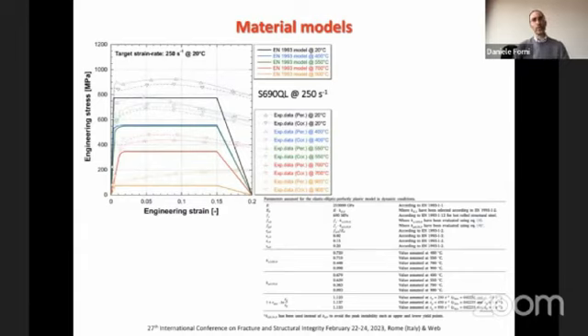So in the first case, for the elastic perfectly plastic approach of Eurocode 3, we have reported an example of the S690QL at 250 strain per second, and we can see that the model we have calibrated can safely predict the real mechanical behavior of the material in the range of the strain and the stress reported on the code.